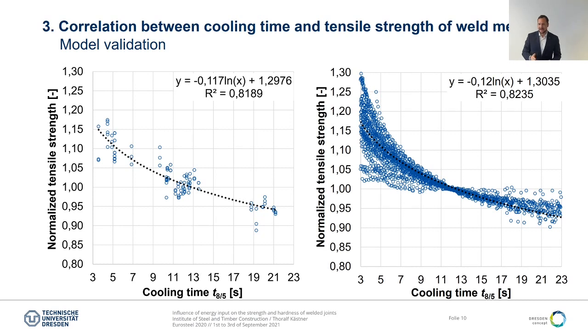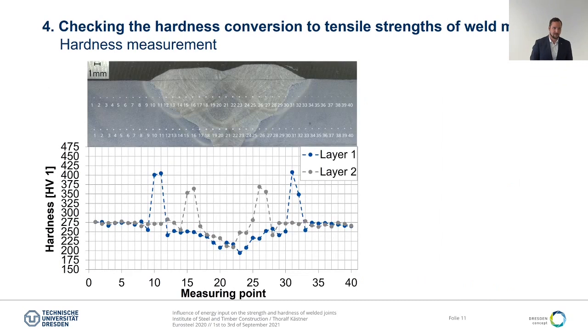Of course, there is at the end a large scattering, especially for short cooling times, which depends on the different filler metals and their different transformation behavior on the crystallization size. But at the end we have at least found a general function to describe this behavior of the tensile strength and the cooling time in general.